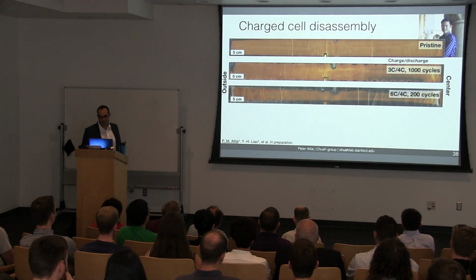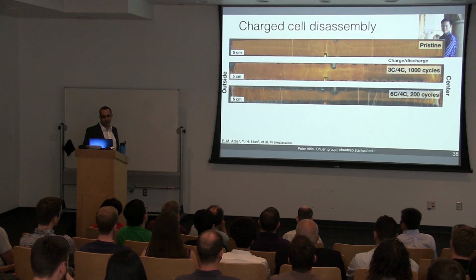Things are getting pretty crazy once you look at the fast charge cell. So after only 200 cycles, we see this really widespread degradation. The edges on both the top and the bottom of the electrode are almost entirely black, which again is inactive.